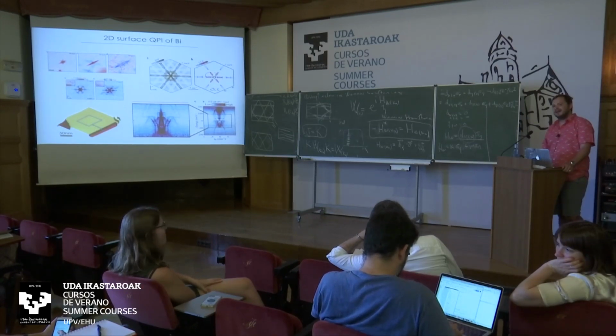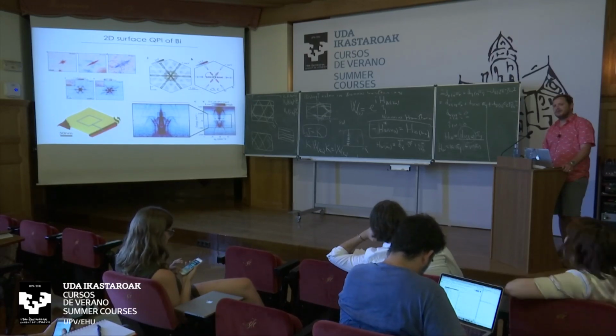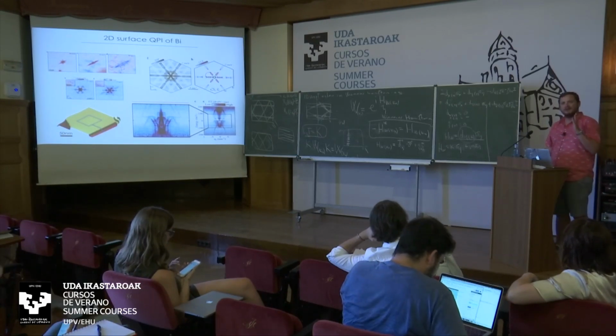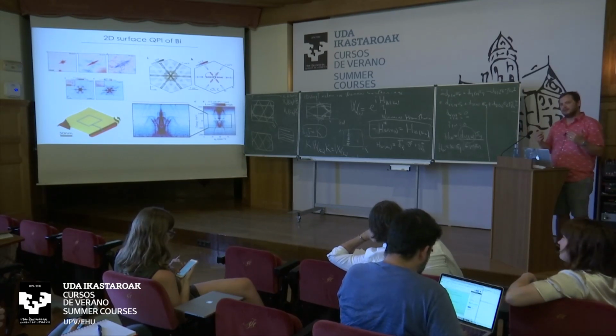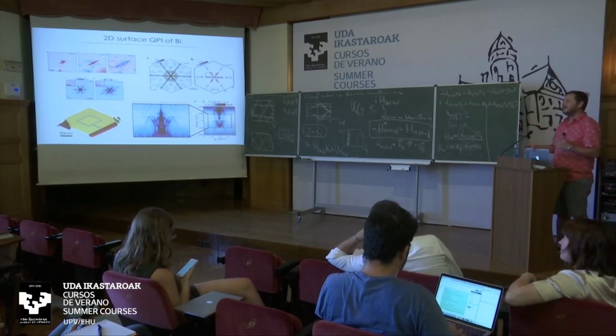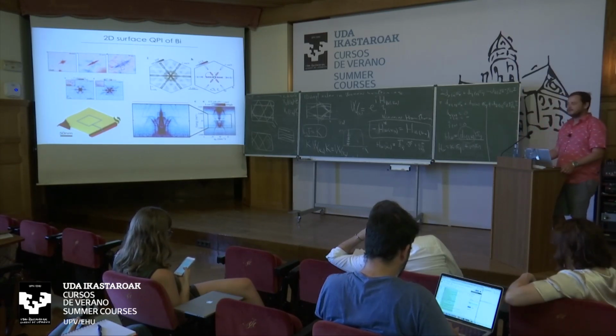Oh, the nematic behavior, or not that? Well, there have been so many works on high TC, so I'm not even sure to which one you refer, but there could be definitely correlations. One difference, I think, is that always in the case of cuprates, at least, you're in the multiple scattering regime. It's a relatively very disordered material, and this is definitely the other limit of ultra pure material, and we see scattering from a single impurity with no other strong impurities around except the step edges, of course.